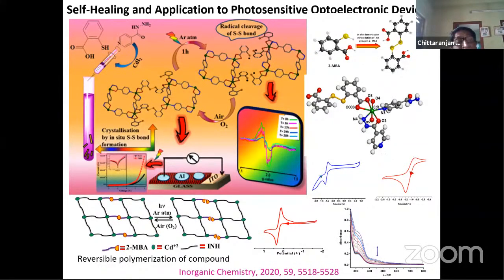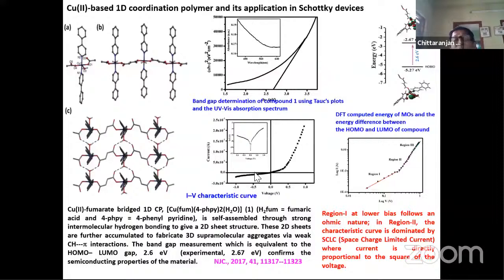That cleavage is responsible for its molecularity, and is responsible for the conductivity enhancement that we could expect, but we have not achieved it at that point because the energy is being used for sulfur-sulfur cleavage. You see this conductivity at the light phase is increased, but the theoretical conductivity is much higher than that of the experimental one, because this energy is being used for the sulfur-sulfur cleavage.